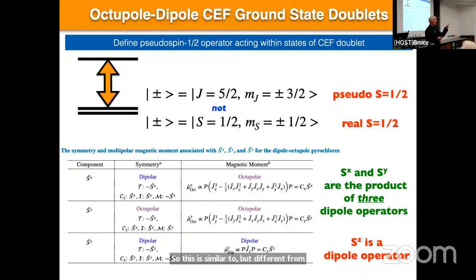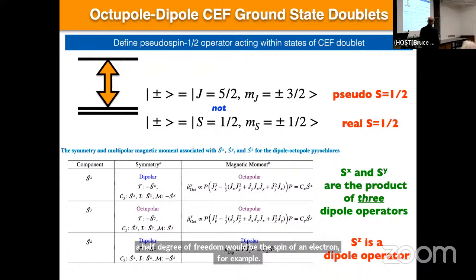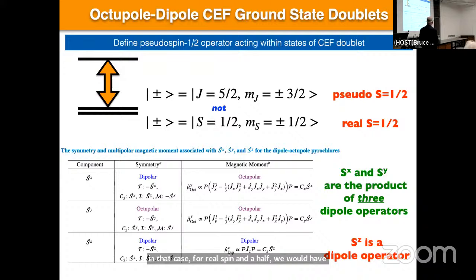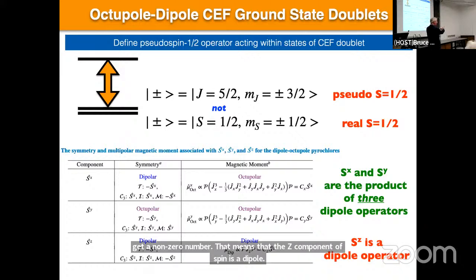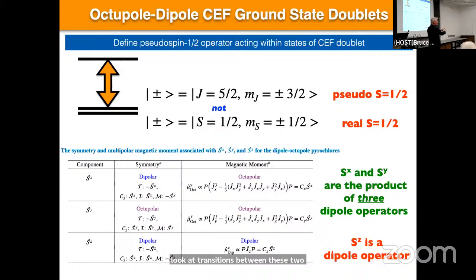So a real spin a half degree of freedom would be the spin of an electron, for example. And in that case, for real spin a half, we would have S equals a half, and the Z component of S would either be plus or minus a half. So this real spin a half has X, Y, and Z spin operators, all of which behave like magnetic dipoles because this is a real magnetic dipole. And what that means is that if I look at the expectation value of Sz within either of these states, I'll get a non-zero number. Okay, that means that the Z component of spin is a dipole, and I can look at transitions between these two states that make up the ground state doublet. And the transitions between them go between ms equals minus a half and ms equals plus a half. So that's an S plus operator or an S minus operator to go in the other direction.